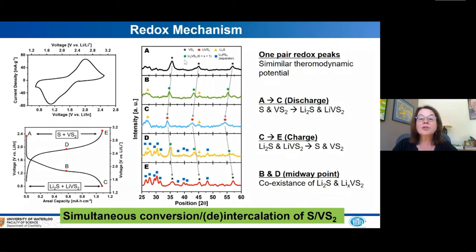Point A is just the starting material where you can see the VS2. The sulfur is a little hard to see here because it's pretty much ball milled. Point B is partway through discharge, and you can start to see these VS2 peaks shift until finally at point C, at full discharge, they clearly indicate LiVS2. We concomitantly form the Li2S, which is indicated by the yellow triangle.